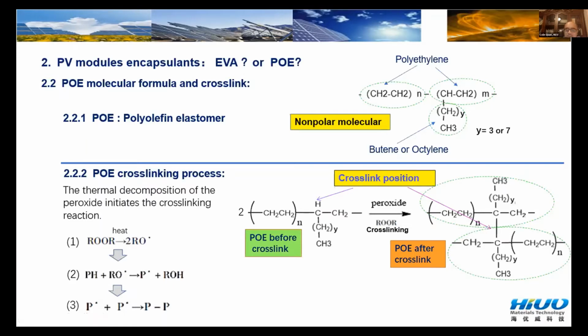As it is a non-polar molecule, it's really hard for the polyolefin to cross-link. So usually when the module makers do some cross-linking degree test, they find the polyolefin, going through the same lamination conditions, gets a lower cross-link degree. For example, generally EVA you can get a cross-link degree of about 85. But polyolefin, you only get maybe 70 or even less. Because their molecule is not so active, it is a little bit difficult to cross-link.